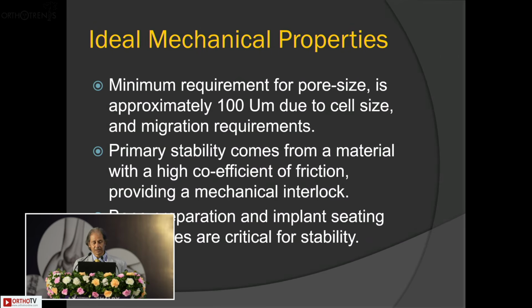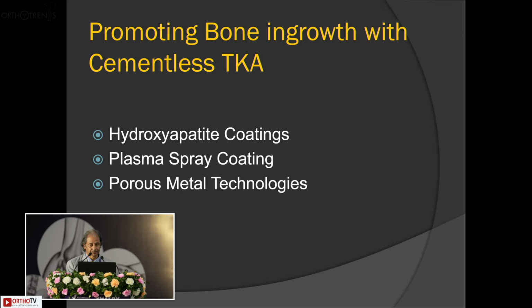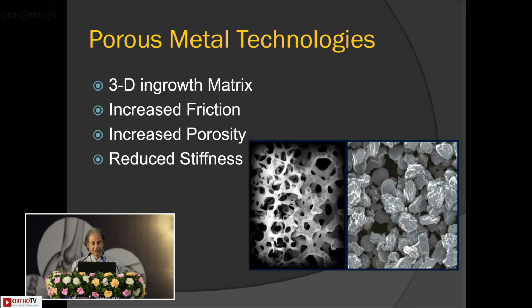So the minimum ideal mechanical property is approximately 100 micron and small sizes that prevent the migration, a high coefficient of friction providing a mechanical interlock, and bone preparation and implant seating procedures which were critical to stability. So today we have these options: HA coating, plasma spray, and porous metal technologies.